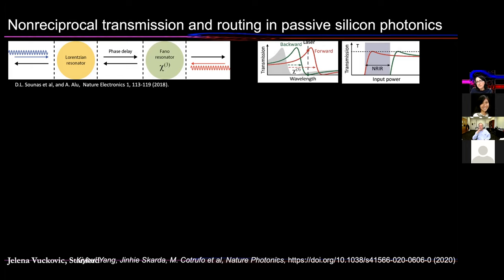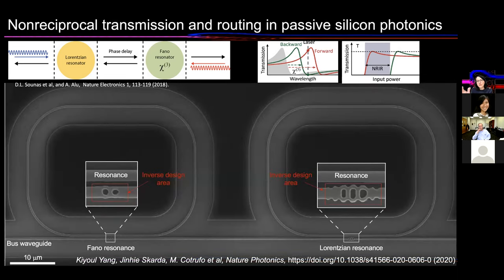And this idea was demonstrated by Andrea Alù's group in microwave, but to demonstrate it in the optical range, we didn't really have known elements that we could simply combine here. But of course, we could rely on inverse design to design everything that is needed, and that's exactly what we did. So we started from a waveguide with two coupled resonators. These are racetrack resonators in silicon, there is a waveguide. We rely here on Kerr nonlinearity in silicon, third-order nonlinearity. And what we're actually doing here using inverse design is basically just optimizing the coupling regions between a waveguide and a resonator by introducing these perturbations into the waveguide in such a way that we achieve desired transmission characteristics for the Lorentzian resonator and Fano resonator.